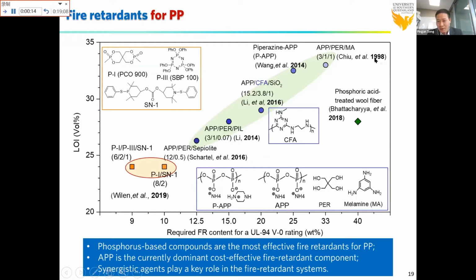In 1998, they reported a combination of APP, whose chemical structure is shown here, ammonium polyphosphate, in combination with PER, a polyol, and melamine as a blowing agent. The PER is a charring agent, and APP is an acid agent. By combining them together at elevated temperature, this flame retardant can produce a foamed char layer. This char layer can serve as a thermal barrier to protect the underlying polymer.